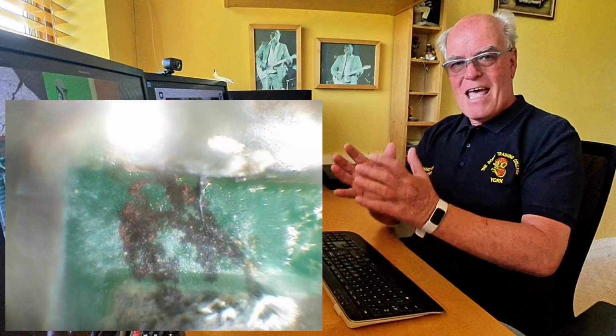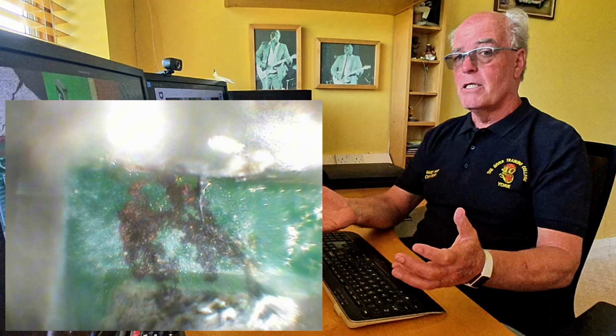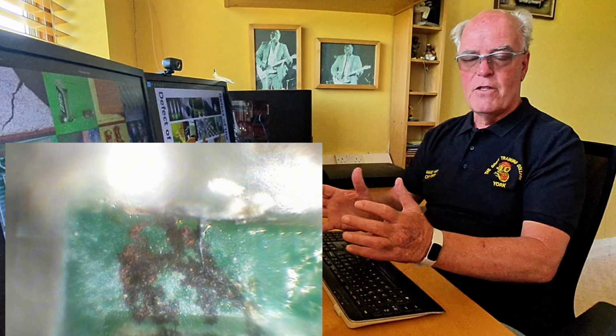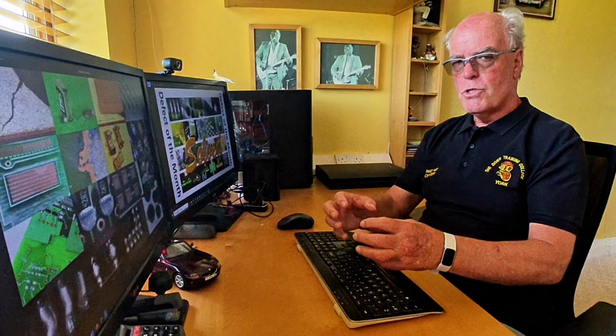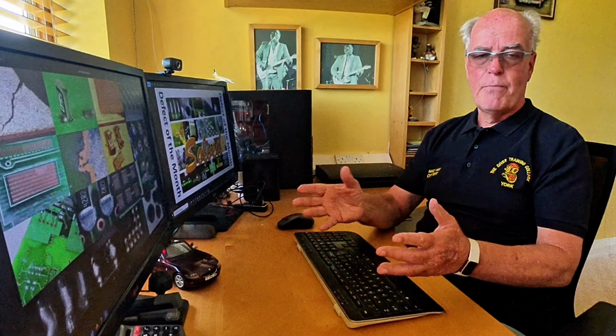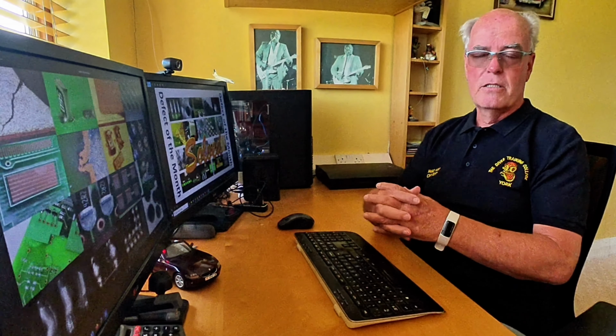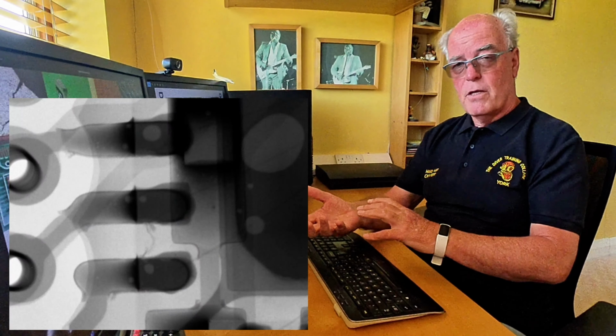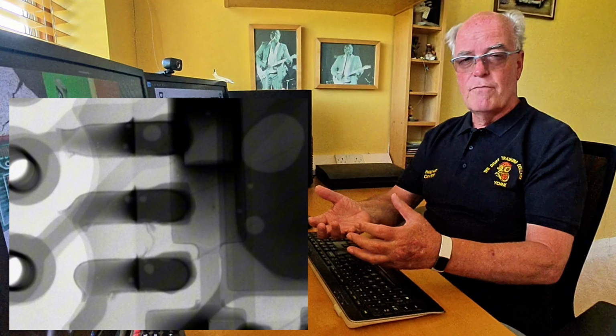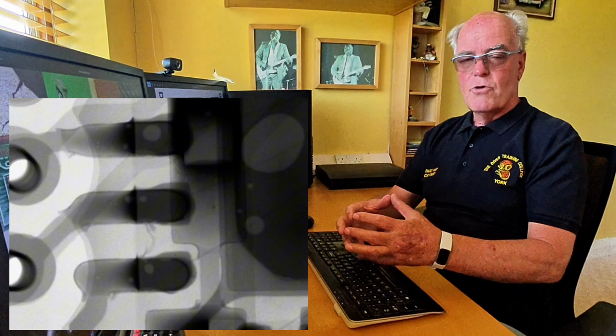When you've done that, that allows you to use traditional optical inspection without damaging any of the information present, and to record the presence of a dendrite. It's also possible to do it with X-ray, depending on the size and density of the corrosion products that are left behind. In this example, I can show a dendrite forming, or has formed, under a QFN package, just back from the area where the soldering operation has taken place.